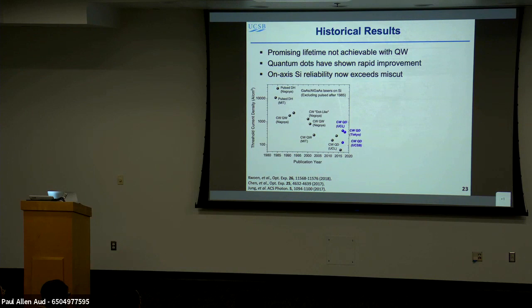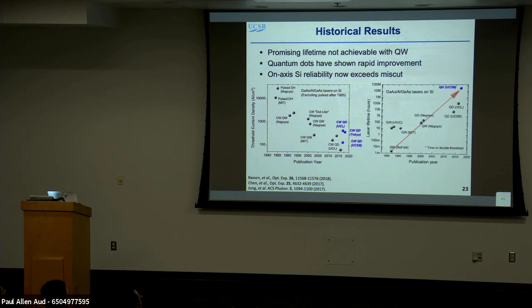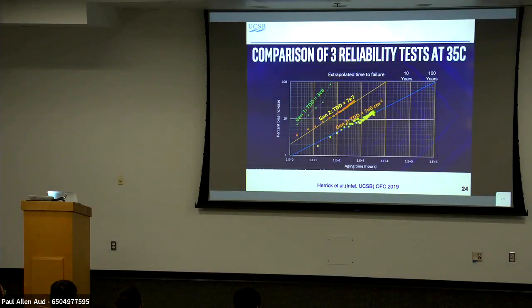So here's the progress over time. Threshold current density. So that used to be 10 kiloamp per square centimeter. Now it's down below 100 amp per square centimeter. That's a really, really good, efficient laser. If you look at lifetime, the best quantum well lifetime has been a few hundred hours, right? There should be one right here, I guess. That's the longest quantum well device. And nothing in the last 18 years has been any better than that. In contrast, quantum dot devices keep getting better and better. And so lifetimes actually are now over 100 million in terms of room temperature lifetime. So there is a huge difference between quantum dots and quantum wells. There's no comparison.